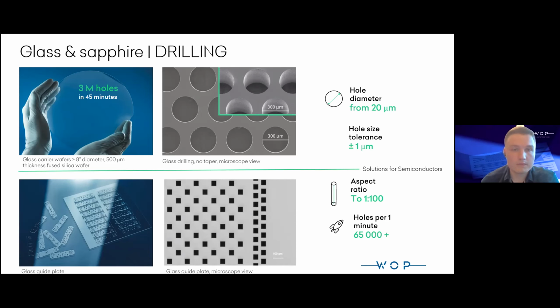Typical size tolerance for holes in sapphire, silicon and glass too are roughly around a micron. Also, depending on the case, these can be even tighter tolerances. So really, the technology brings you to the edge of what's possible to be done, at least these days.